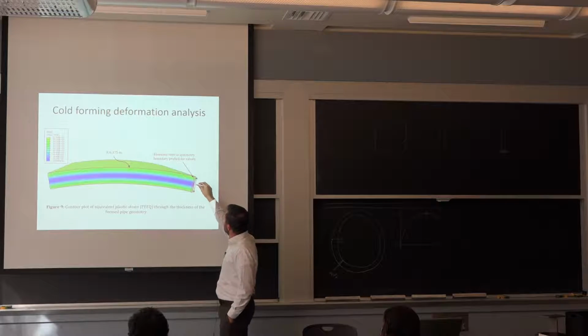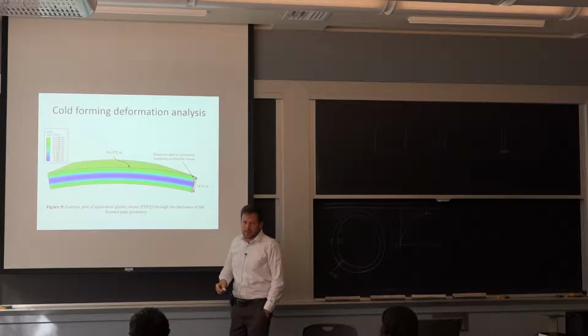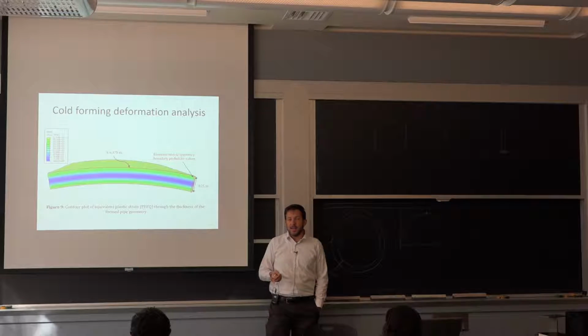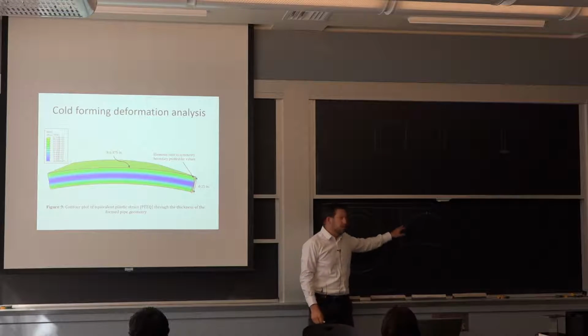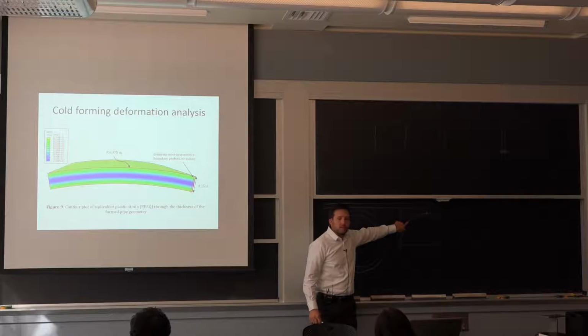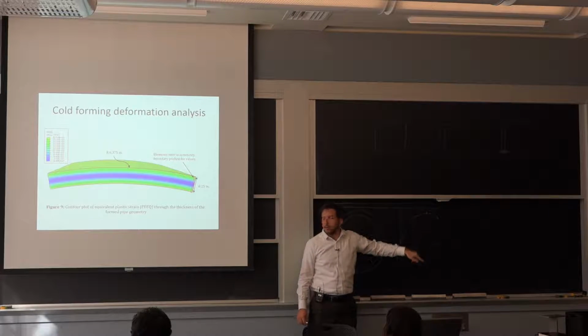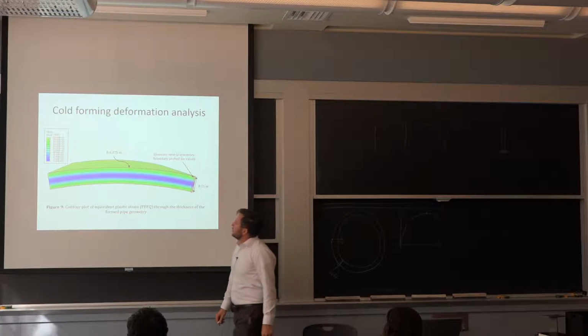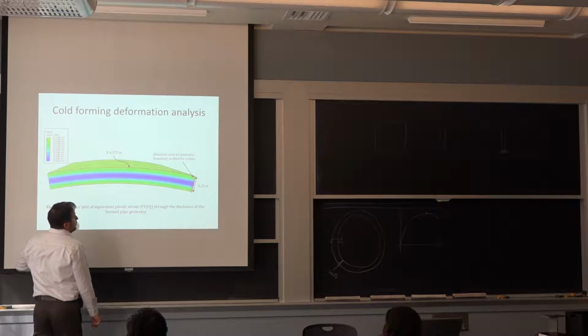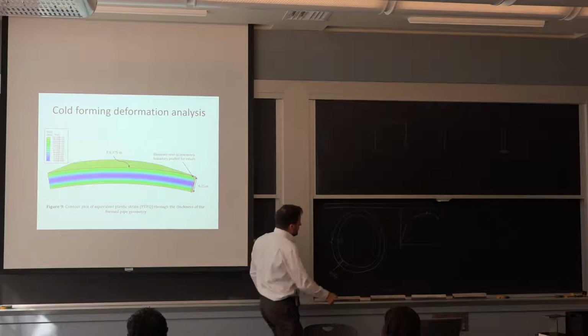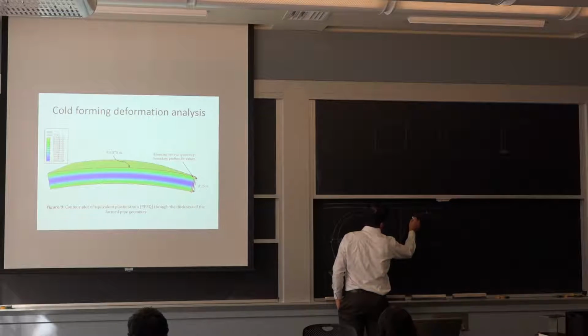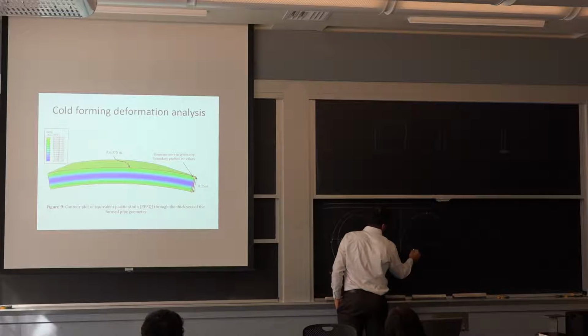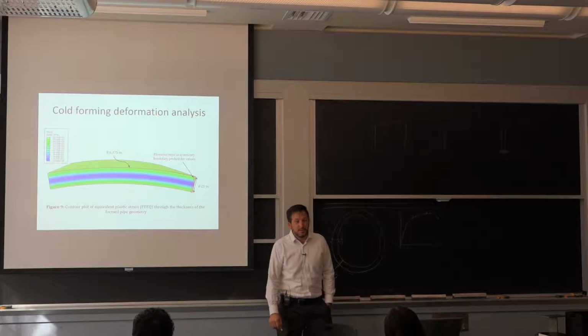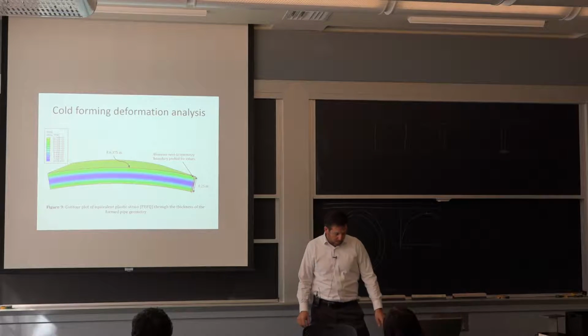So we got essentially the center core, only about 1/5 of the thickness, that remains only in the elastic region. So when you see blue, it means that you're below the yield point. And then everything above is above the yield point. If we go to our strain level here, 2.2%. So we only went about this far. So can that explain the hardness profiles?